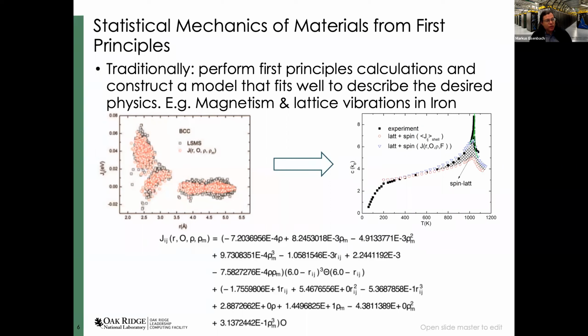At the same time, of course, the atoms are moving around, vibrating. So this will affect the magnetic interactions of the moments on the individual sites. To do this, we perform first principles calculations here using LSMS, for many atom displacements and varying the atomic order to determine the magnetic exchange interaction, the Jij, between all the different atom pairs in the system.